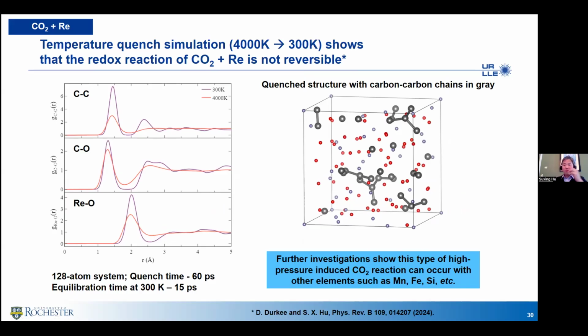One more interesting finding is that he also did this quench. He took this QMD at 4,000 Kelvin with the rhenium in there. Remember, this is CO2 already dissociated. Then he ran the QMD and lowered the temperature, back to room temperature. What happened to the system?